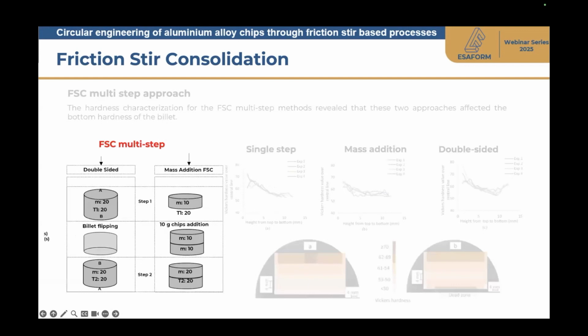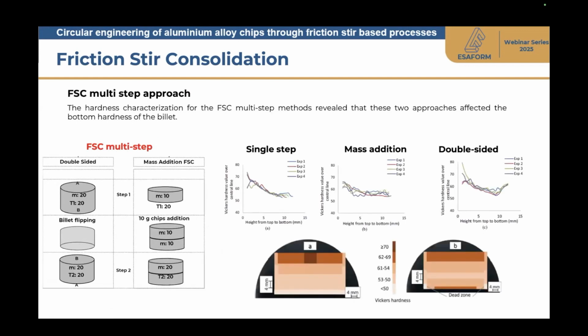Well, in the multi-step approach, as you see, the idea at the end was to get a flatter trend of the Vickers value from the top to the bottom of the billet. This is the trend, which is quite steep in the single step approach. Both in mass addition and double-sided, but in particular in mass addition, we have a definitely flatter trend of the material hardness in the consolidated billet, and this shows it is possible to improve the mechanical characteristics of the billet itself, just modifying the approach of the process.